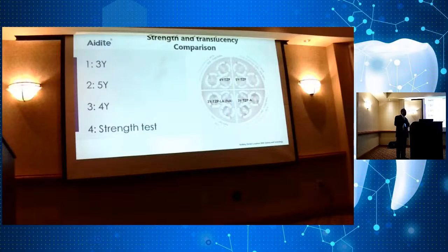So here, in my opinion, I feel that if you can find a material that is good at everything, okay, it has the perfect amount of translucency, you can adjust the translucency in your CAM software, or you want to have a material that's over 1,000 MPa or 1,050 MPa and above. Okay. Anything less than that is suspect, especially if you have very thin proximal areas, and also it's not going to have great translucency. So in my opinion, I think you need to use a hybrid material,